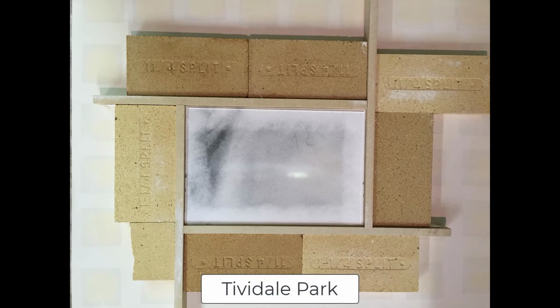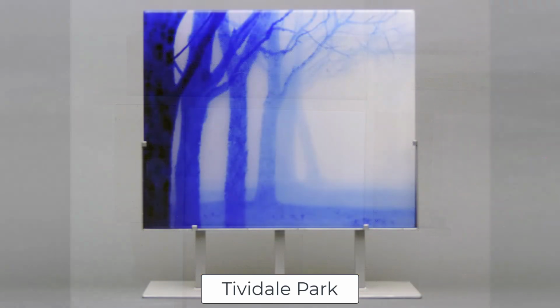But for my 20-layer pieces, such as the Grand Mosque, the cooling process takes 5 days. And of that, 4 days is spent annealing the glass. And there's no peeking allowed. Here is a photo of Tividale Park after it is stacked in the kiln and surrounded with brick and ready to be fired in the kiln. You can't see the image clearly because it is covered with a sprinkling of clear glass powder, which looks white due to light reflections. But once it is fired, the clear powder does show clear and provides a smooth and glossy finish to the front of the artwork.